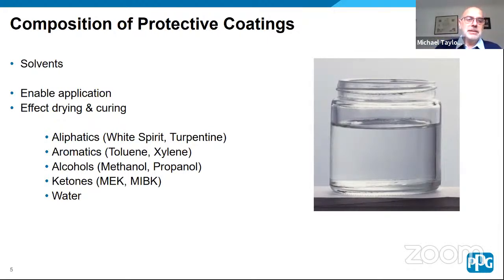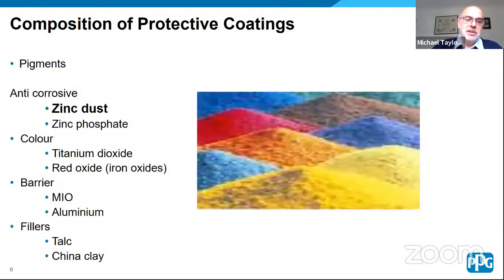And the third main ingredient is, of course, the pigments. This presentation today is mainly around zinc dust, which is used as an anti-corrosive pigment. But there are also other anti-corrosive pigments. Most common is zinc phosphate. In the good old days, we used to have lead and zinc chromates, very effective anti-corrosive pigments, but now they've been phased out, quite rightly, for health and safety. They're not the nicest pigments to work with.